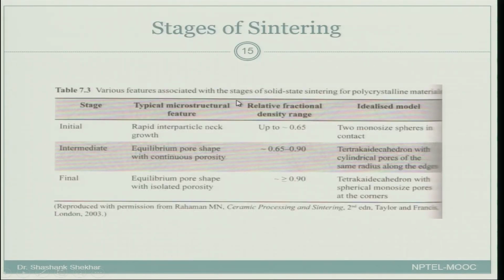We will now summarize the 3 different stages of sintering. In the initial stage, there is rapid interparticle neck growth, and the relative fractional density may reach up to 0.65. Two mono-sized spheres in contact is our idealized model. In the intermediate stage, the equilibrium pore shape has continuous porosity, so you have a network of porosity, and your fractional density may reach 0.65 to 0.90. The idealized model is a tetrakaidecahedron with cylindrical pores of the same radius along the edges.